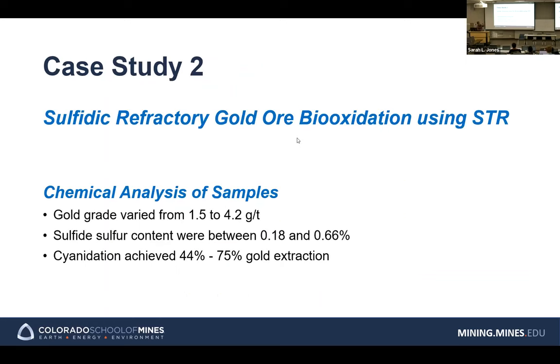And the second one is about refractory gold ore biooxidation using stir tank. So stir tank, if you remember, I said, uses fine ground material in a well-controlled system. Chemical analysis: the gold grade varies from 1.5 grams per ton to 4.2 grams per ton, and the sulfide sulfur was pretty low, 0.18% and 0.66%. The sulfide content is not high. I mean, with this sulfide content, we expect a pretty good cyanidation result.